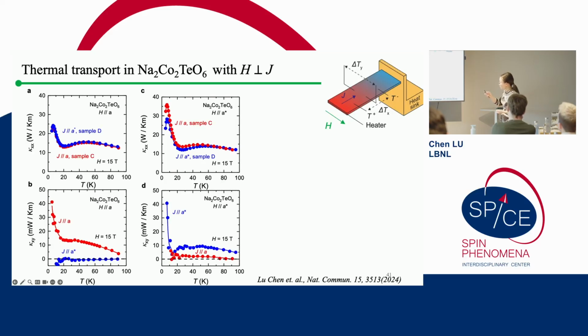So what we did here is, let me use panel A and B to tell you the first set of results. Panel A is the thermal conductivity versus temperature taken in 2 different samples. For both samples, the field is applied along the zigzag direction, but the only difference is where the heat current was applied. You see that when we change the heat current direction, thermal conductivity itself is more or less isotropic. It almost didn't show any change.